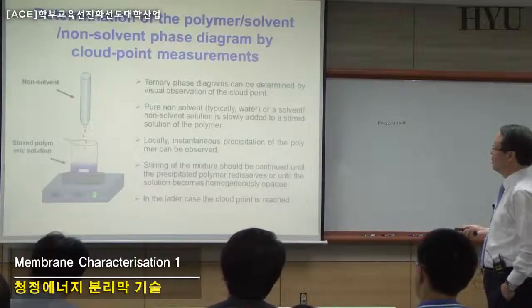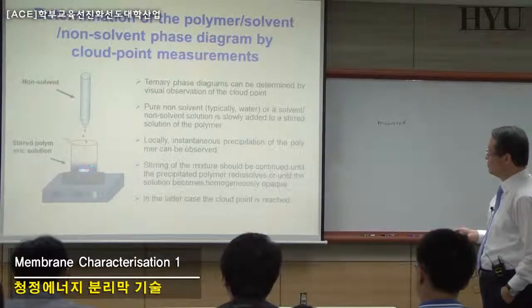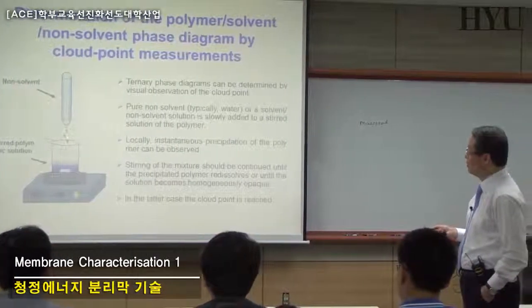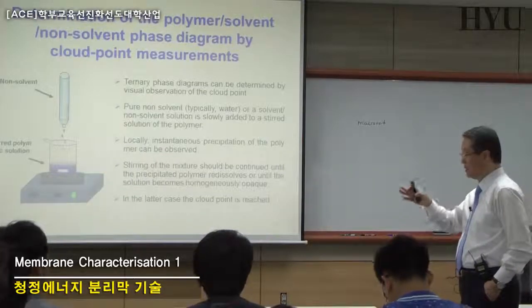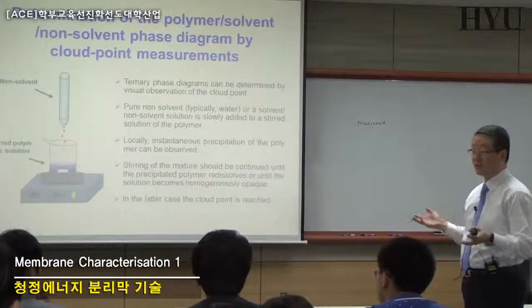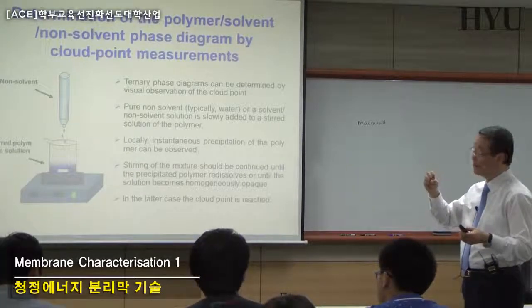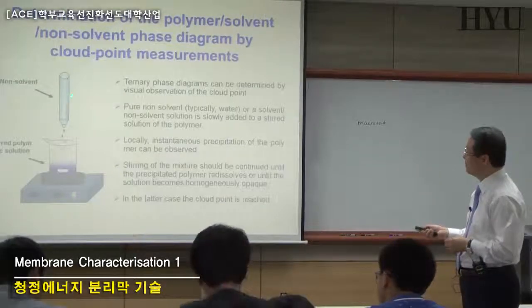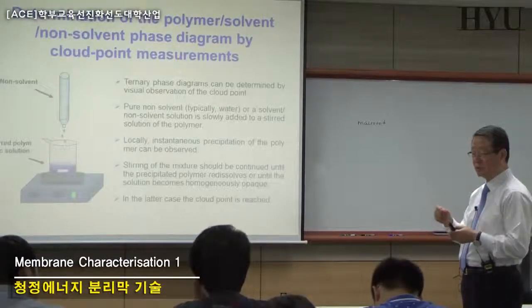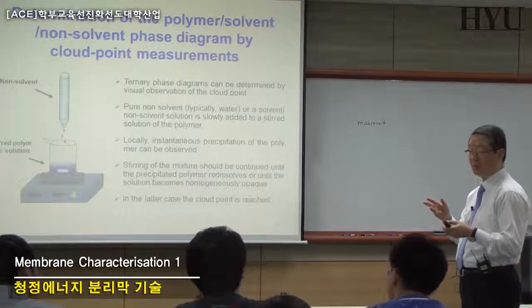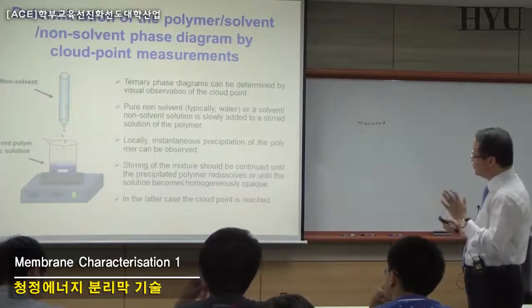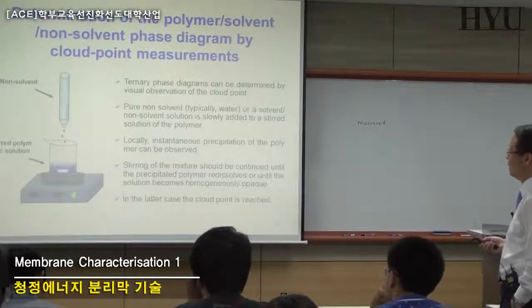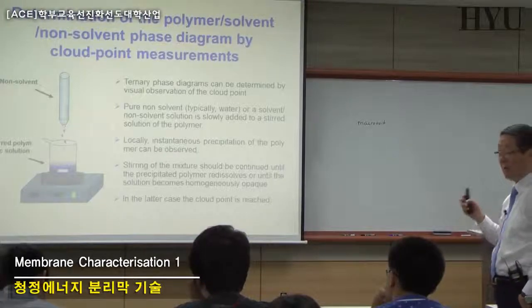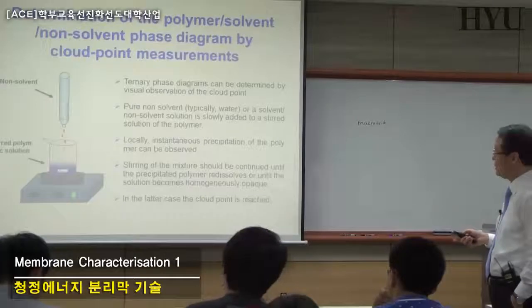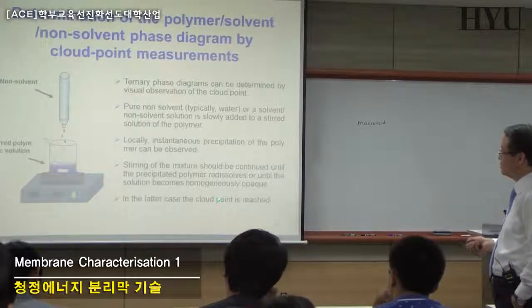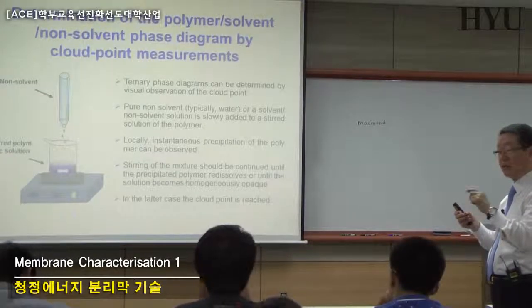cloud points. Usually, when you have a polymer and solvent and make a polymer solution, you drop in your non-solvent. When you drop the non-solvent in a small quantity, nothing happens, right? But after reaching a critical quantity of the non-solvent added to this stirred polymer solution, you start to see some precipitation points. Okay? The starting point could be recorded as well as the final precipitation points, and it's not easy. So the cloud point is the point where your final precipitation occurs.